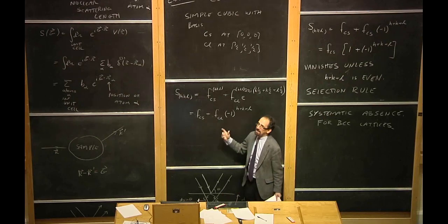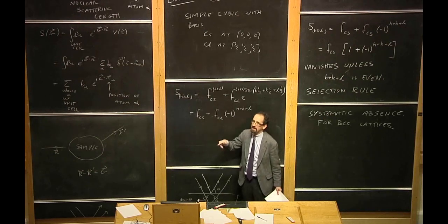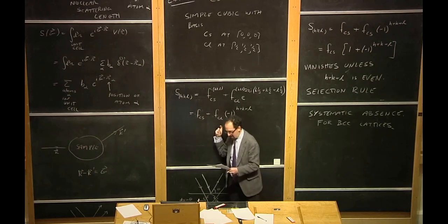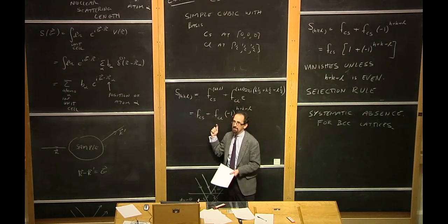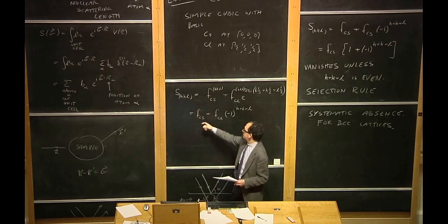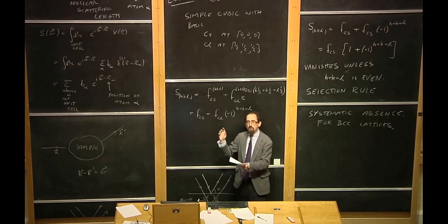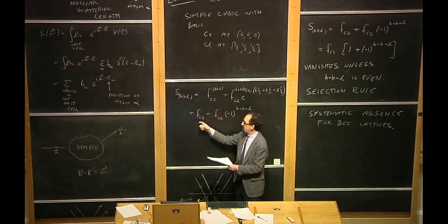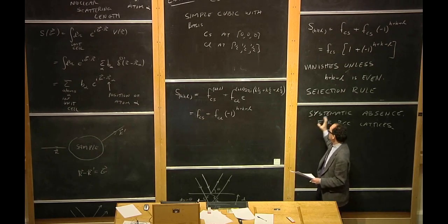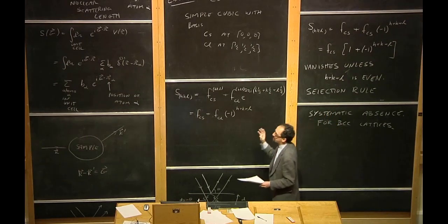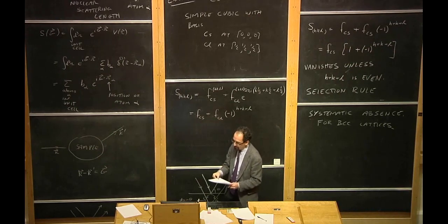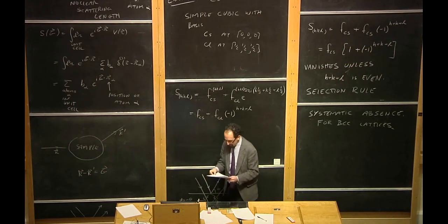It's cesium chloride. If you replace chlorine with iodine, which is two spaces under it on the periodic table, the iodine has atomic number 53 and cesium has atomic number 55. So the cancellation between these two would be almost exact. Only within a few percent you would have a slight non-cancellation. So it's very easy to make the mistake and look at the data and think that you have a BCC lattice because you think there's a systematic absence. But if you look at it much more closely, you discover that, in fact, it's not perfectly canceling. Okay? Everyone happy? All right.